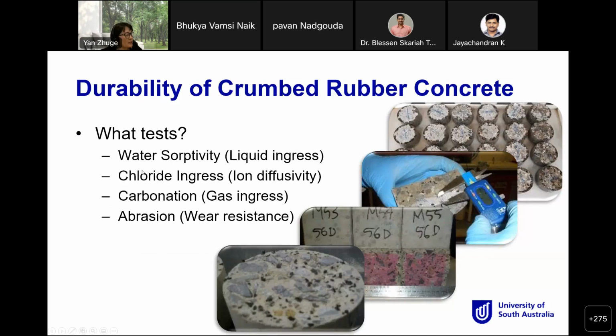So what tests did we do? We did a water sorptivity test, which is called liquid ingress. And we did a chloride ingress test as well to look at ion diffusion or leaching analysis. We did a carbonation test, and also we did an abrasion test to see the wear resistance if you want to use them as a pavement. So these are the 4 major durability tests we performed.